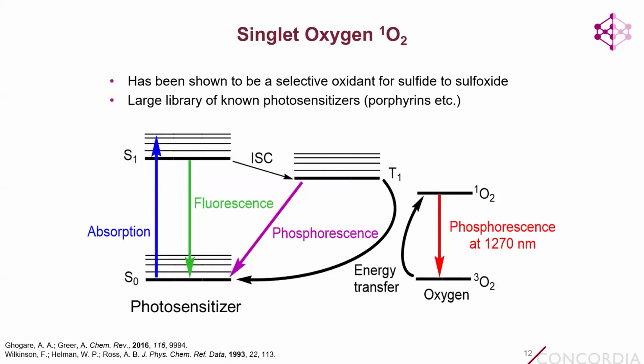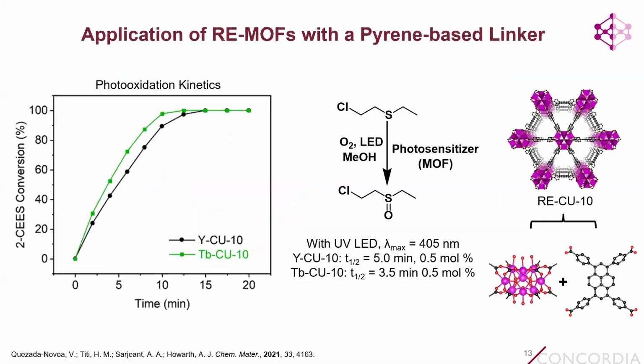And if that triplet state has the right energy, it can transfer its energy to ground state triplet oxygen, generating singlet oxygen, which is a reactive oxygen species, and can do this selective oxidation. And so Victor takes his metal organic frameworks, in this case, rare earth Cu10, which has these pyrene-based photosensitizers. He suspends them in a methanol solution, adds the mustard gas simulant, shown here, and then bubbles the reaction with oxygen for 20 minutes to make sure that it's an oxygen-saturated environment.